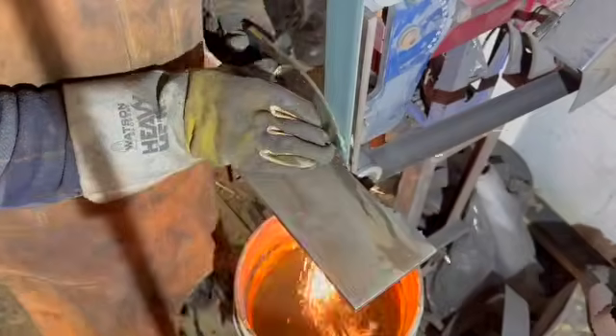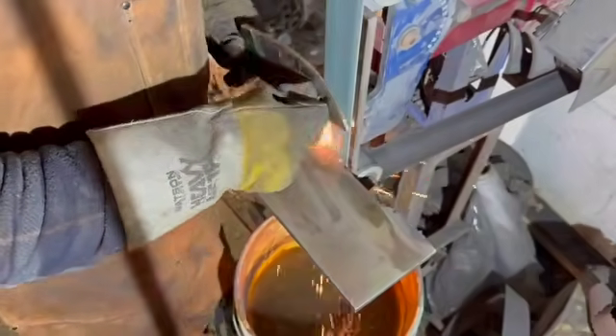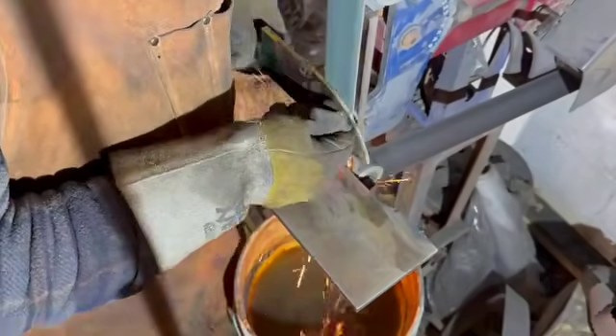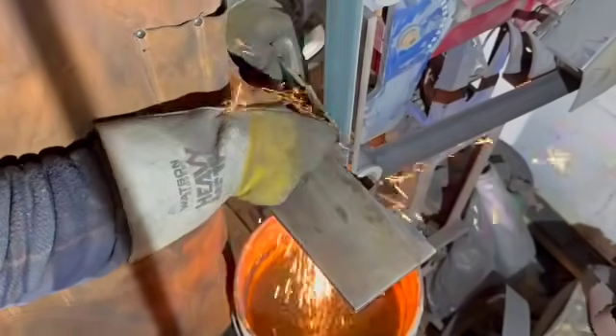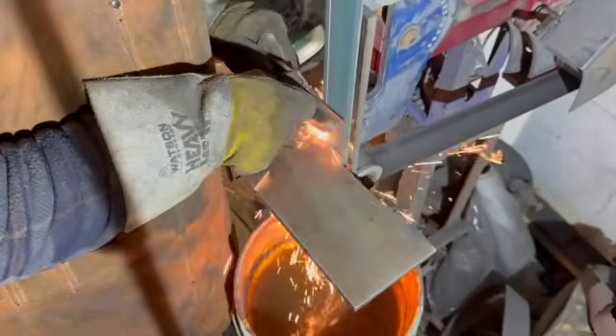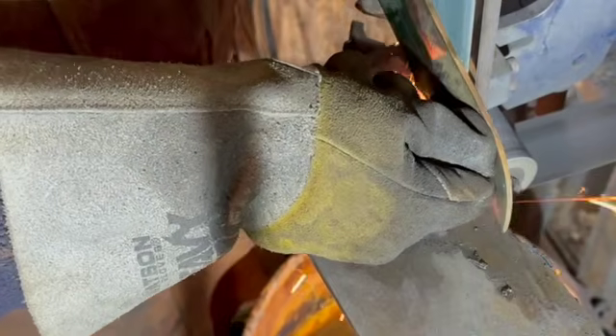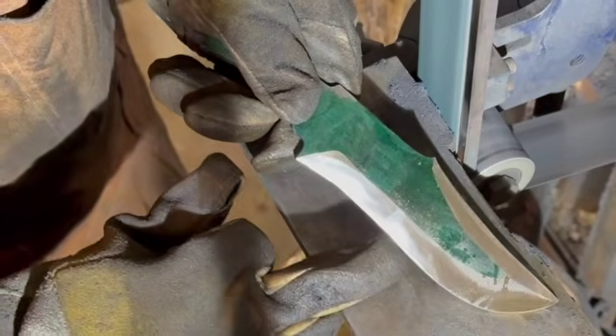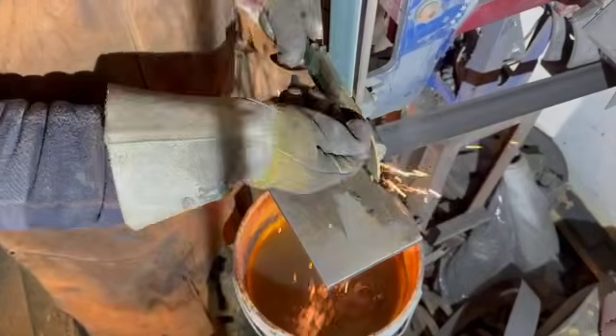I find when grinding San-Mai, one of the things you have to do is watch your temperatures. Steel and copper heat up at different rates, and the last thing you want to do is create any more stress between those layers and have them potentially separate on you. So lots of dunking when you're grinding. I always get excited when I'm grinding and I see that copper start to peek through. I'm trying to keep that 1084 steel in the center of the blade, and you see that copper rise up on the edge.